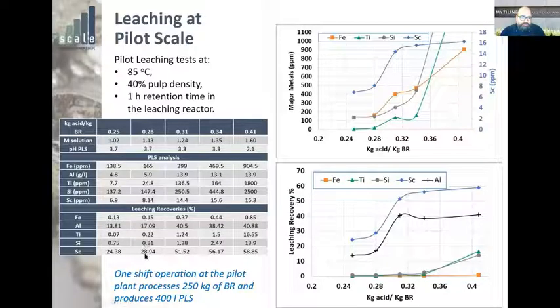This means that we have a recovery of close to 30%. But if we go a bit higher, you see there's a huge incline where you can get 50% of scandium, but at the same time, your iron is doubled and your titanium is tripled or quadrupled. Therefore, this is a very steep increase, which also threatens to throw away the results of the resin.